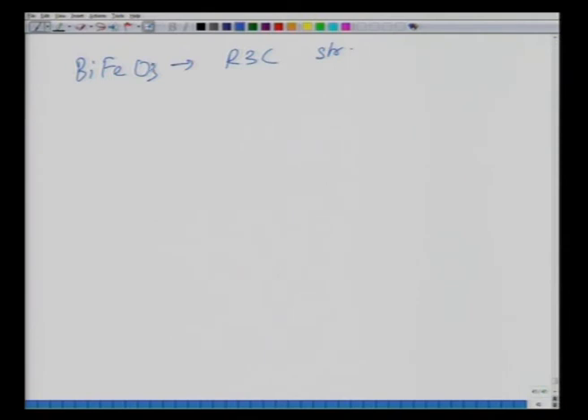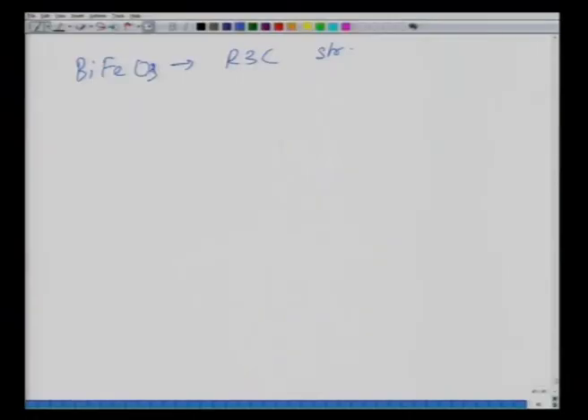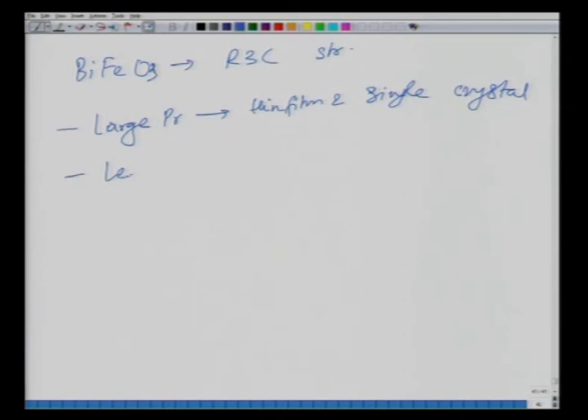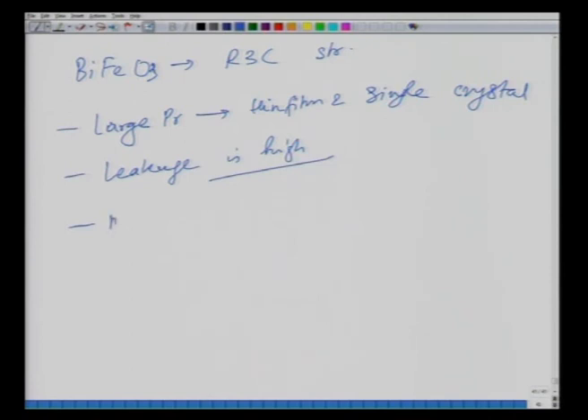Now as I told you, in thin film form this material has been shown to exhibit high polarization, but the magnetization which was reported in that study was later found to be wrong because the authors did not notice the presence of impurities. However, making this material is not easy. So although it has large Pr in both thin film and bulk single crystal state, the leakage is high, and leakage could be high because of defects, impurities, or grain boundaries. So as a result, making this material is not easy. One has to be really careful in making this material in good quality, and if you can control the magnetic impurity formation precisely, then in pure form the magnetic moment is negligible.